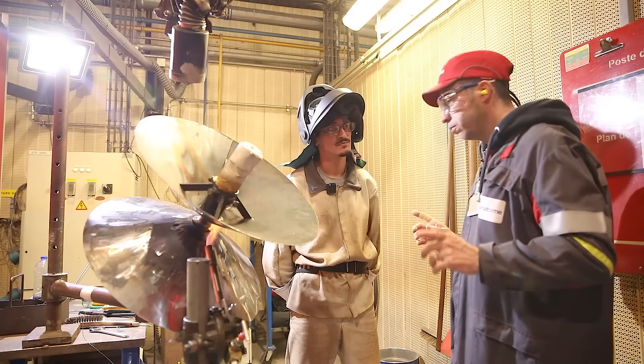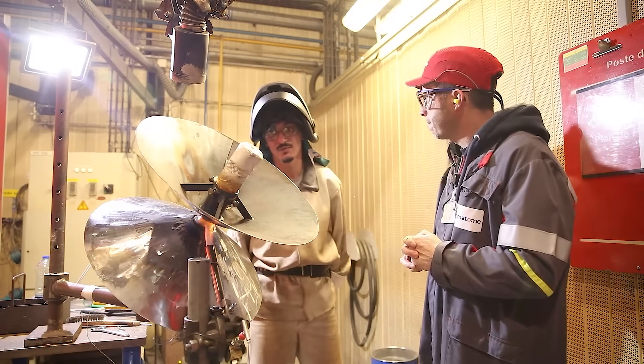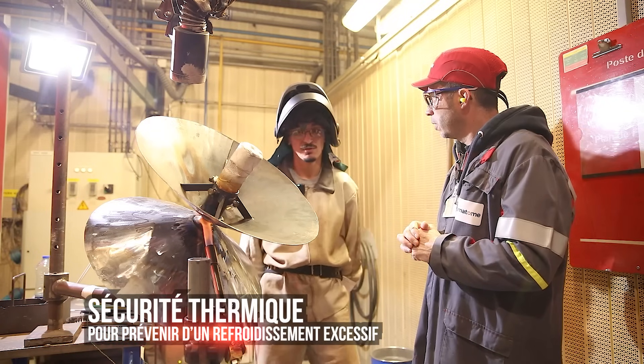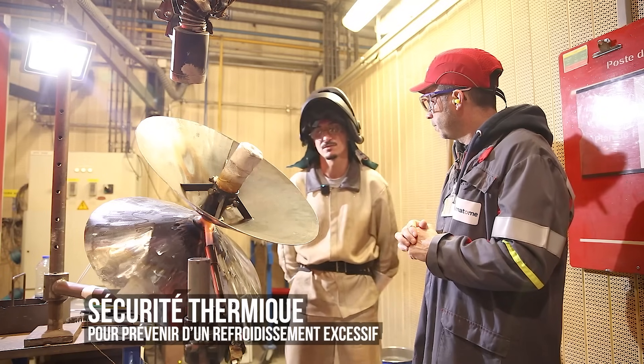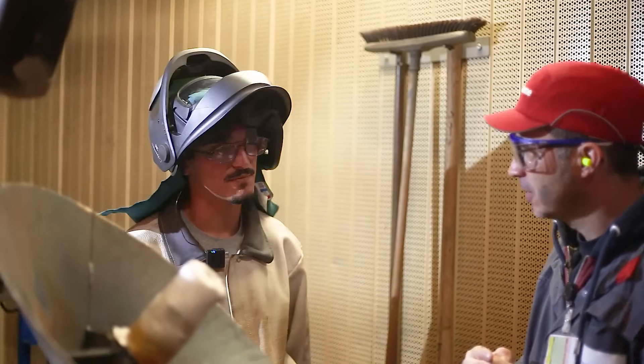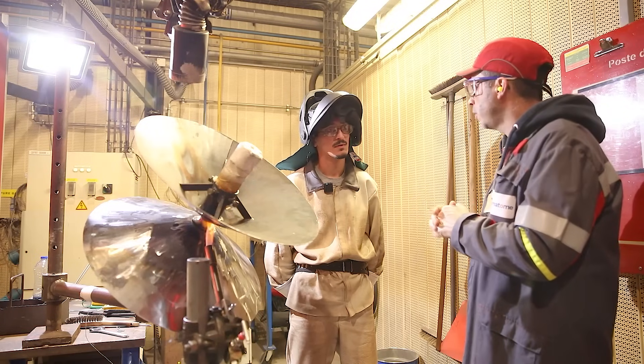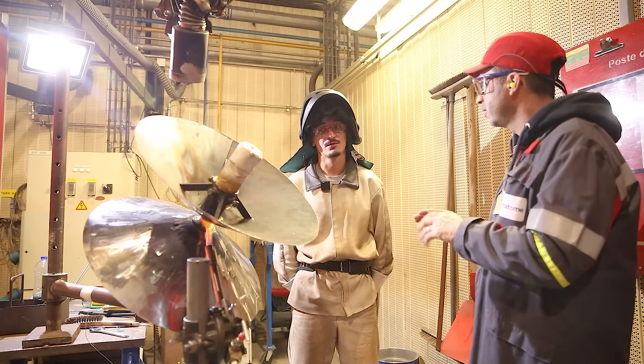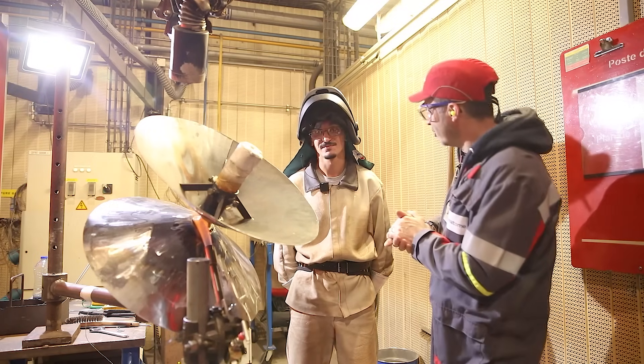There's a wire connected to an alarm that warns Aymen if the piece temperature drops too low. The minimum is 150°C and he has set his alarm at 160°C for added safety. He has been with the company for two months — a very new recruit. He currently has two qualifications to pass; this is the first one.